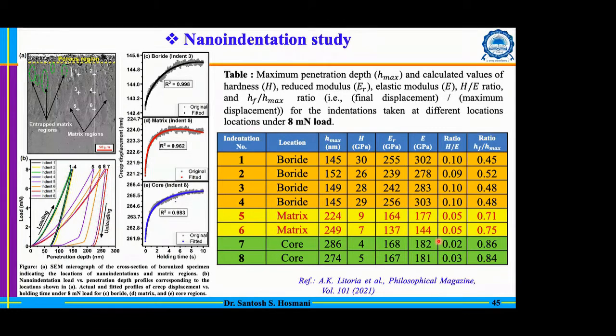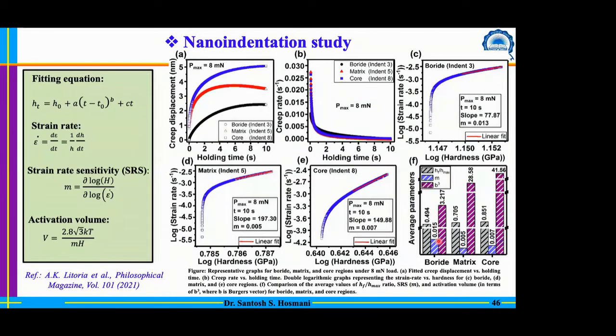And the matrix definitely has different properties. That is because of the segregation of elements. Whenever material is lost and fresh material is exposed to the surface, your surface has the boride as well as a matrix, which have different properties. Even though the matrix appears like a boride-free region, its properties will be different because of the segregation of the element. Depending upon the chemistry of your alloy, you will have different properties of this matrix, and the response during application will also be different.